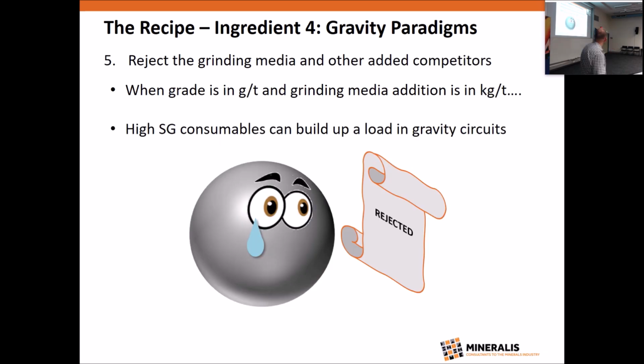And number 5, reject the grinding media and any other competitors you've added. And if you're dealing in grams a tonne and you're throwing in kilograms a tonne of steel, you're adding a lot of competition. Admittedly, this is not generally done commonly these days, and it's a bit pointless and difficult in high capacity gold gravity circuits using high G-force concentrating devices. But in the old days, it was quite common to see a magnet over strakes and tables to avoid recovering the steel into final gravity concentrates prior to smelting.